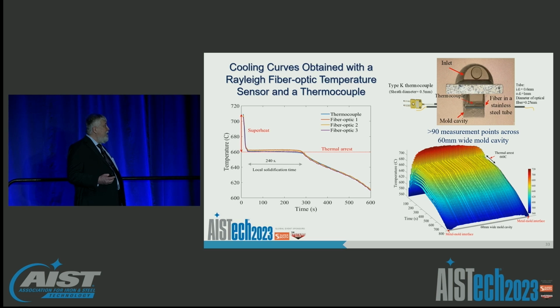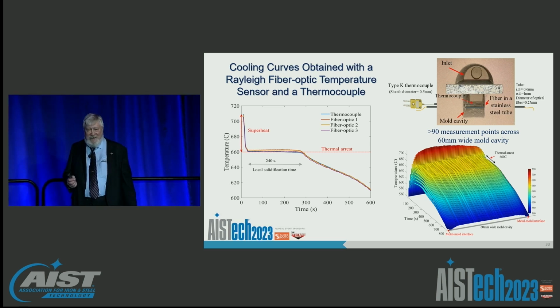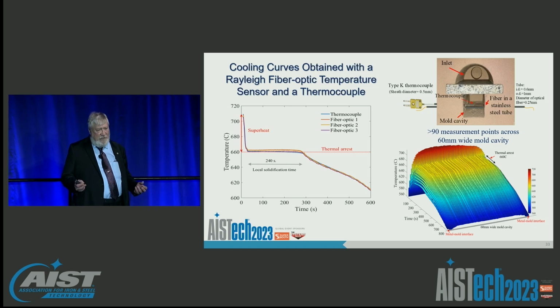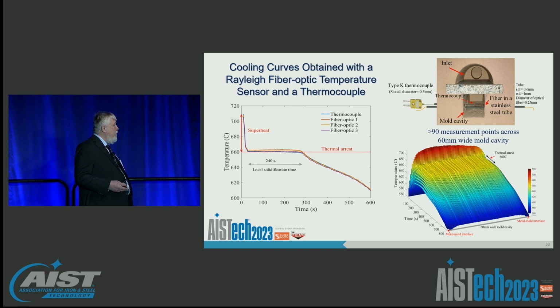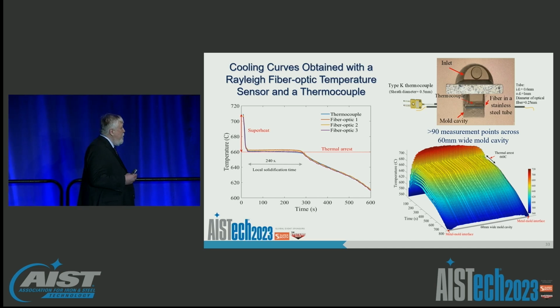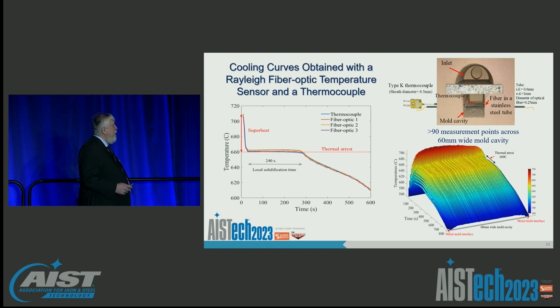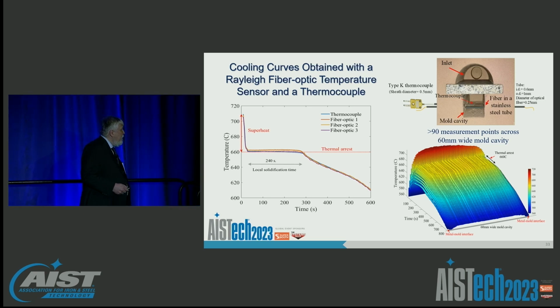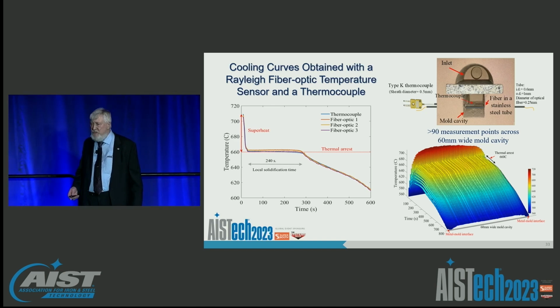And this is actually an aluminum casting, sorry guys. But given that the fiber has temperature measurement capabilities of about 700 C, this is actually a really good test to show what the single fiber is capable of in a solidification environment. And so we've actually put a fiber across the mold cavity and measured the thermal arrest associated with solidification, in this case for a relatively pure aluminum. And you can see, of course, the arrest shows a pretty good uniformity right where it's supposed to be at about 660. And the nice thing is on the lower right, you can actually see the variations in the local solidification time, all extracted with a single fiber.